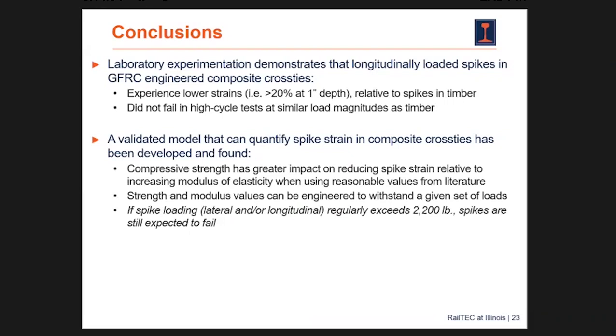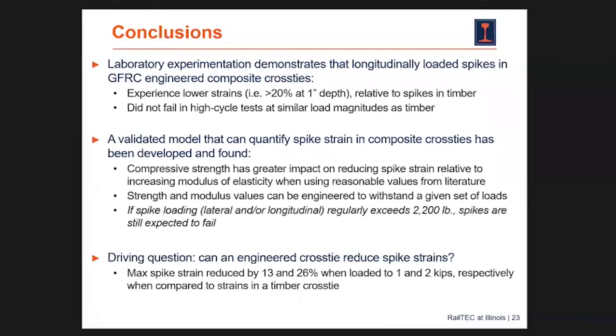composite cross ties do experience lower strains. They didn't fail in cyclic tests, and our validated model showed that compressive strengths have a greater impact on reducing the strain than modulus. And ultimately, if we ask the question, can composite ties potentially be used to mitigate broken spikes? The answer is yes, potentially, but definitely more work would be needed out in the field to see, is this going to work? And is it economically feasible to be able to do so?